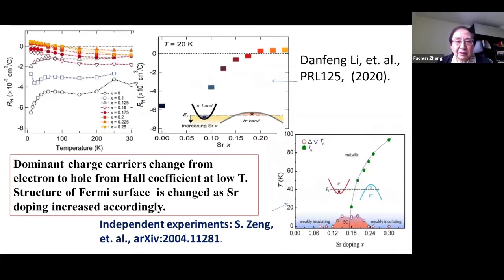The same group, Daifeng Li and Harold Huang, made this picture to show two types of carriers. The upper left panel is a Hall effect measurement, and they plot the Hall effect as a function of strontium doping x. You can see this is some kind of electron picture and this is some kind of hole picture. So the data can be measured from the Hall experiment. That means the dominant charge carriers change from electron to hole when you increase the doping x.